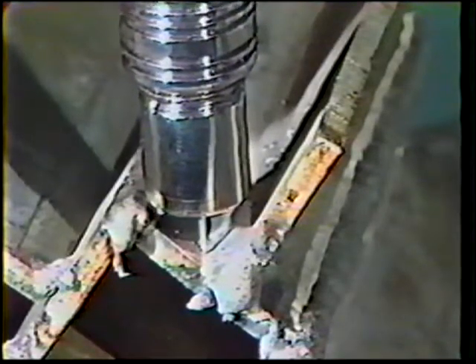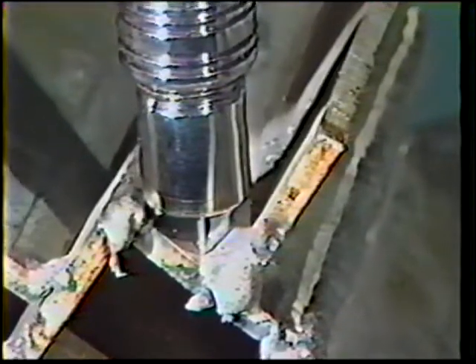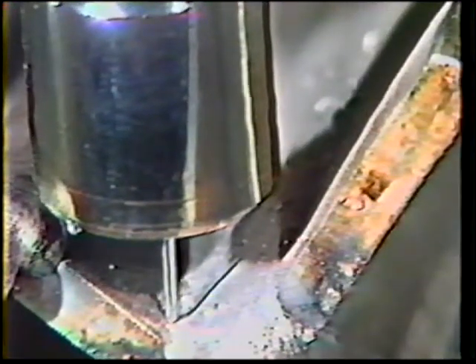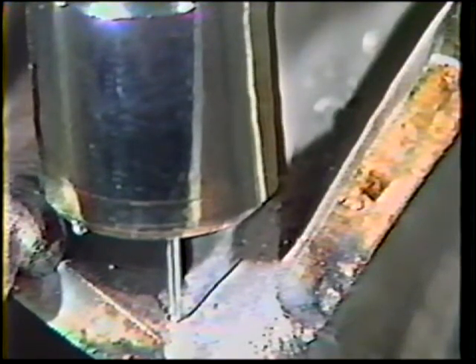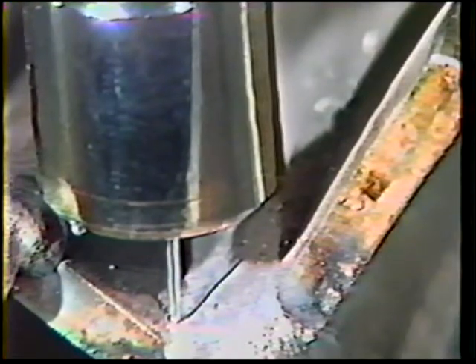The third and final pass will use a 30 to 40 degree work angle, directing the electrode at the toe of the first bead in order to overlap one-half of the second pass. The travel angle remains the same as before. Travel smoothly and evenly along the joint, using a very slight weave if necessary for proper fill. The complete T-joint should have a face that is flat to slightly convex, smooth and regular, with no undercut along the toes. Inspect the weld and continue practice on the remaining workpieces.